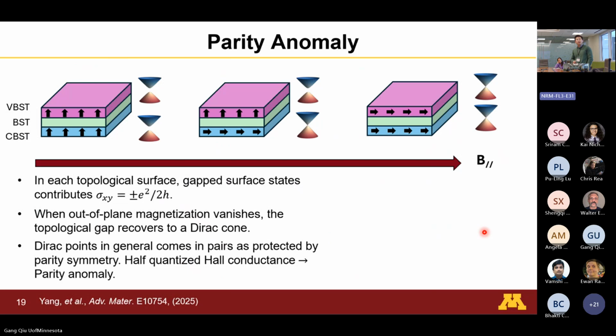So it turns out, again, it relates to something in particle physics, right? So if you look at the band on the surface states, with the quantum anomalous state, we mentioned that the magnetism will gap out the surface Dirac states, right? So you have a little exchange gap here. Now, when you rotate the magnetic field, the chromium layer first becomes in-plane, right? Now this will close this exchange gap on the bottom layer. So you have a Dirac cone on the bottom, and a massive Dirac gap, or gapped Dirac states, on the top.